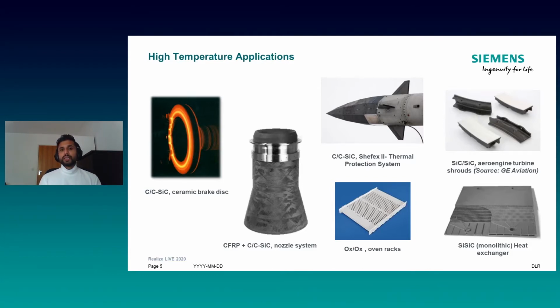Another example of CMC is aluminum oxide fiber embedded in aluminum oxide matrix, known as oxide-oxide. We can produce oven racks where we can place our samples, and because of the high temperature stability, the rack itself would not deform over a longer duration of time. Another potential use of CMC in general is silicon carbide fiber embedded in silicon carbide matrix. Industries such as GE Aviation have already been using these components in their aero engines. In this manner, they can achieve higher efficiency with reduced weight and lower emissions.